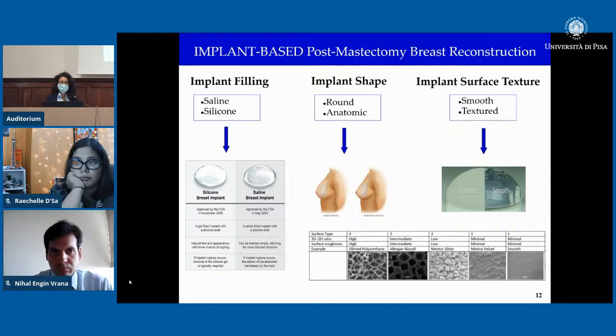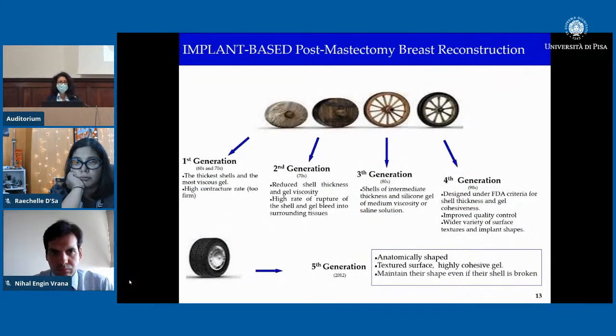And these silicone implants have evolved into different generations based on the shell thickness and gel viscosity, because the first generation used in the 60s and 70s was characterized by the thickest shell and more viscous gel, and they felt too firm compared to natural breast, and they were associated with a high incidence of capsular contracture. So the second generation was developed that was characterized by reduced shell thickness and gel viscosity. But because of this thin impermeable shell and less viscous gel, they were associated with a high rate of shell rupture and gel bleed into the surrounding tissue.